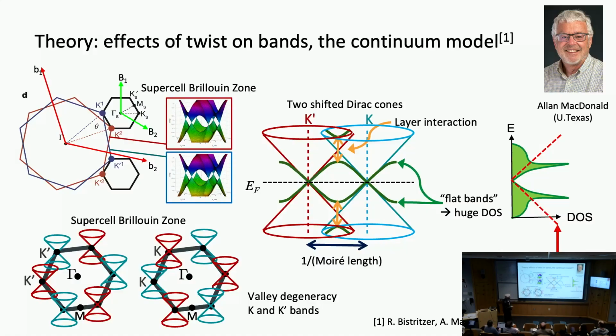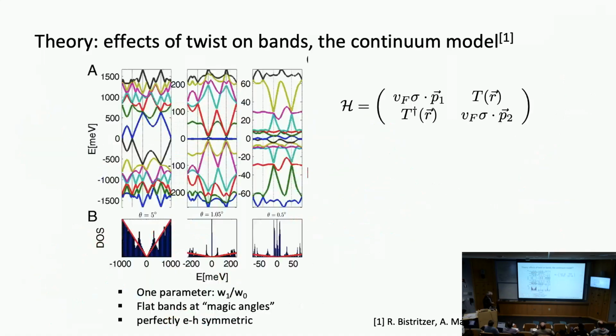Moreover, this range where this enhancement happens is a tiny, tiny energy range because the bands are so flat. In fact, the bands, as you'll see in several examples in a few moments, have dispersion of the order of a few milli-electron volts. And this is certainly very easily accessible experimentally. So that was the huge discovery, the huge realization.